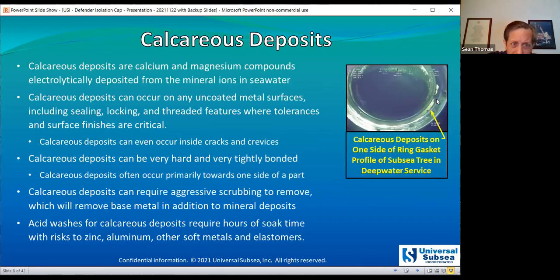So we talked about some of this. Calcareous deposits are calcium and magnesium compounds. They can occur on any uncoated metal surfaces, and can even occur inside cracks and crevices. Do you guys have any experience with calcareous deposits in the field? They can be pretty tightly bonded and fairly hard, and generally require pretty aggressive scrubbing to remove. The problem is that if you're scrubbing to remove calcareous deposits, you're also removing base metal, and that can affect your manufacturing tolerances, which is important, as we'll see.